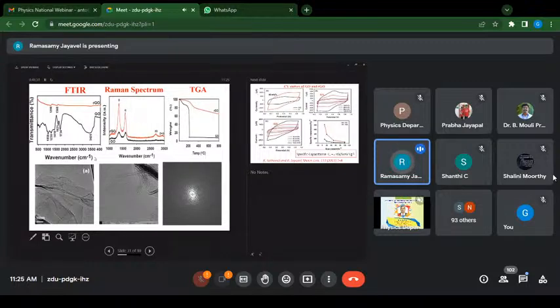And then the Raman spectrum can also be used to confirm the formation of the graphitic layer with the G and D bands. And if we have a single layer, we get only the graphitic peak in Raman. And if you have a stacking of multiple layers, obviously you have defects, and then these peaks are also observed. And the stacking also leads to some overtones like the 2D and D plus G peaks, which appear at the higher wave number side. And the reduction can also be checked by thermal analysis.